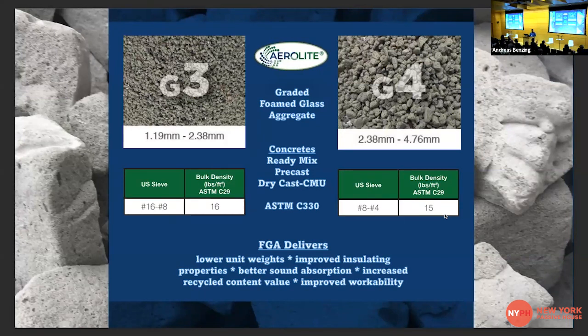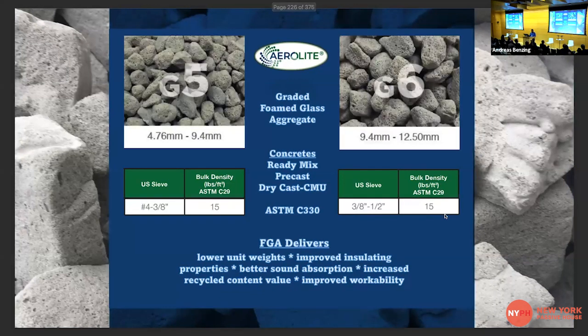And this material recently this year, we just got our ASTM C330 approval. So foam glass aggregate is now approved as a lightweight aggregate for use in structural concrete. And then, of course, as the particles get bigger, you get a little bit more insulation value and the unit weight goes down. The particles get smaller, the unit weight goes up a little bit. But at the bottom here, you can see no matter what product you're using it for, it lowers the unit weight, it improves the insulation properties, it absorbs sound, and it's 100% recycled content. So if you're going for LEED points, this is the material.